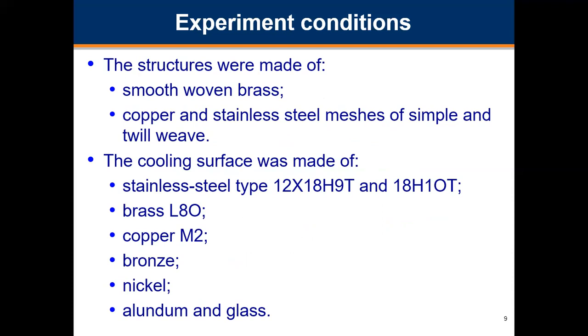When studying the beginning of liquid boiling, the number of net layers was up to 9. The cooling surface was made of stainless steel, brass, copper, bronze, nickel, alundum, and glass. The wall thickness was 0.5 to 1 and 2 times 10 to the power of negative 3. The balance discrepancy between the heat supplied by steam in the condenser and the heat removed by circulating water did not exceed 11%. The material balance discrepancy between the coolant flow rate, discharge flow rate, and condensate flow rate did not exceed 10%.